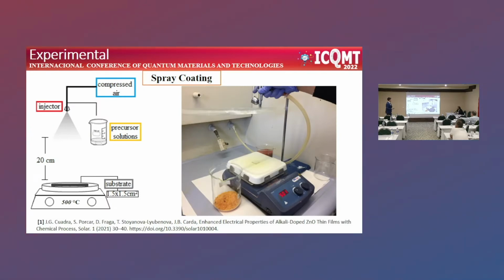Well, how can I do that? The method to synthesize this type of thin films is spray coating or spray pyrolysis. We prepare a precursor solution and we apply it with a spray, with a handmade method. Why do I use this method in comparison with, for example, CVD or physical vapor deposition? Well, this method is totally applicable for industry. If you talk with an industrial, as you say, if your method needs, for example, high vacuum or something like that, probably it doesn't work, because industry doesn't work with this type of methods. This is a method used to produce glass and ceramic tiles, so it can be applied really easily in industry.